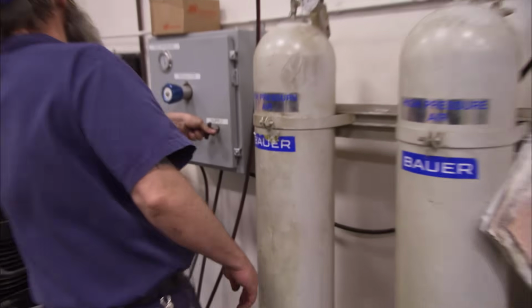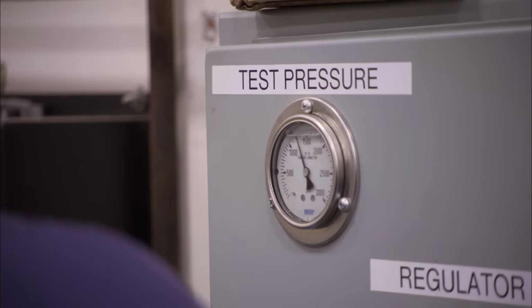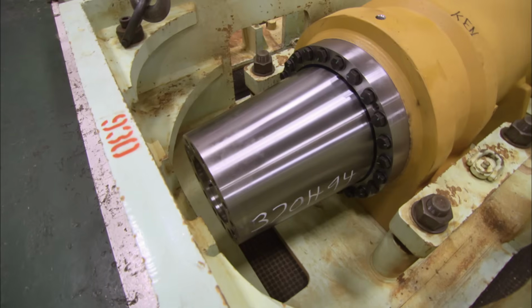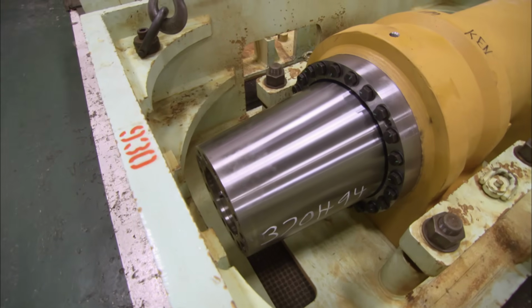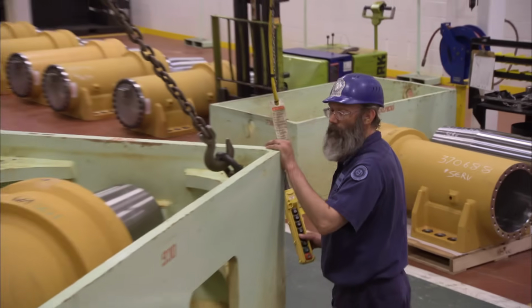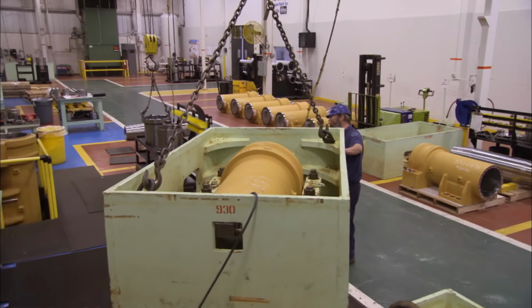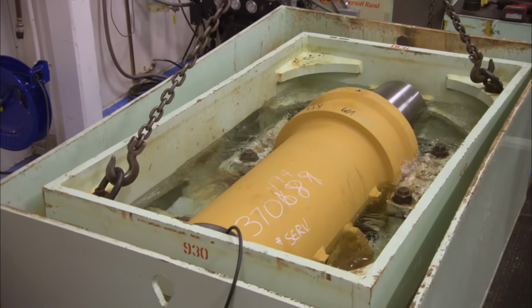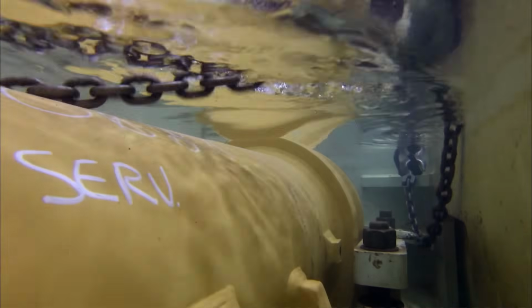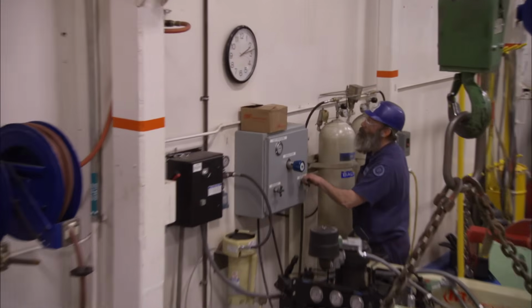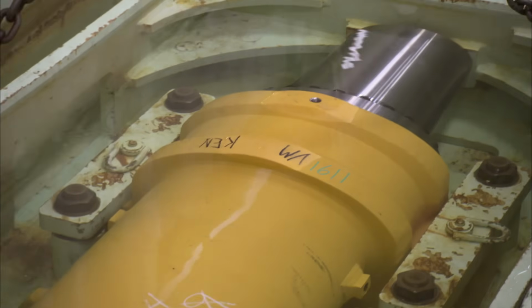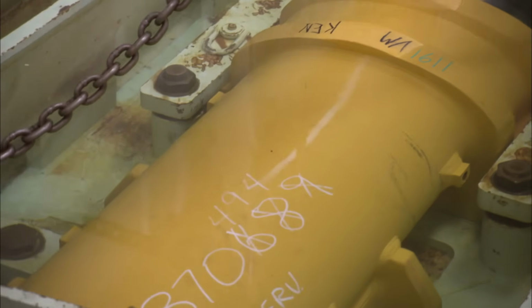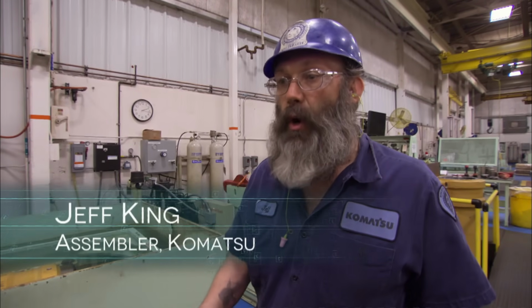1,100 pounds per square inch of air pressure is injected into the suspension, and the cylinder keeps the 3,000-pound chrome-plated piston from firing out like a rocket. Next, searching for leaks, the cylinder is carefully lowered into a 500-gallon tank of water. It has to stay under pressure for 20 minutes. If we have no bubbles, we have no troubles.